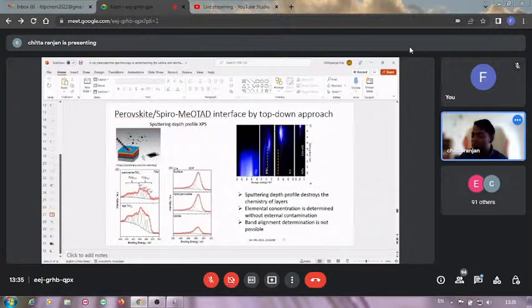Like what we do in the case of sputtering, you sputter with an argon ion, and then you remove the material, and then you measure. For example, here we measure carbon, and then keep on sputtering, and then at some point we don't have any carbon. Similarly, here it was gold, like you can see the gold, and when we keep on sputtering, then gold is removed and the lead is visible. At some point lead is removed, only titanium is visible. So from here we can say, okay, what's the thickness of each layer and how they are behaving.